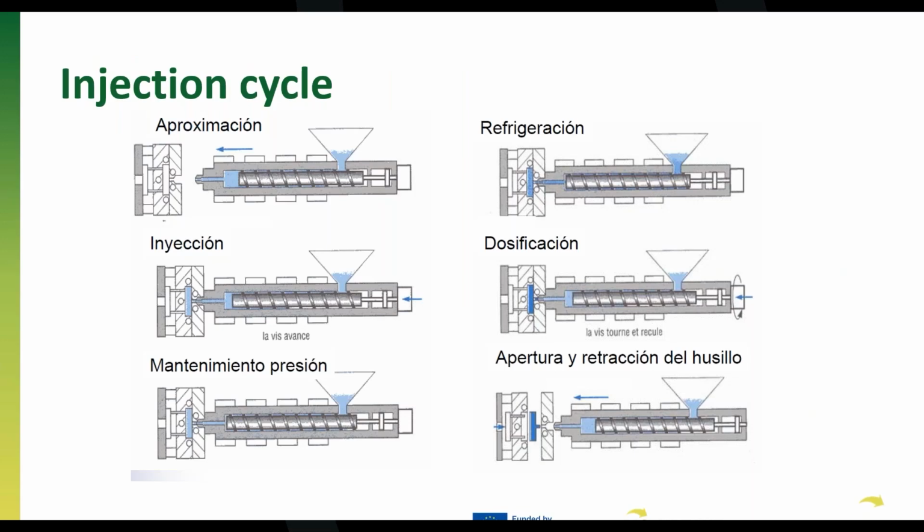In the case of the fossil-based materials, in some cases, you can fit more material into the screw and keep the material in the screw melting and molded at those high temperatures. In the case of bio-based material, it's better to make the injection faster and try to avoid this degradation in this sense. Of course, it depends on the material. Okay, I'm talking generally.